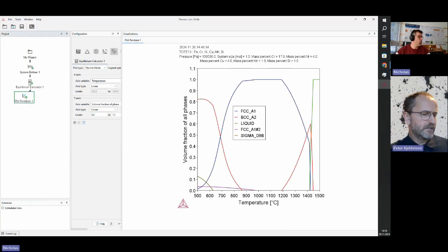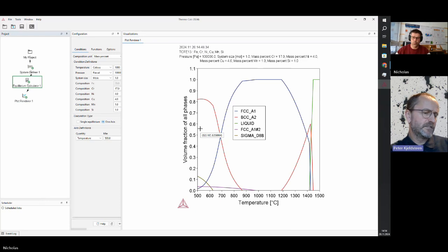Yeah. And we have, I think it's called a ferritic steel. I think you can make it magnetic, but typically it is used as a ferritic. So okay, the hardness of it comes from the precipitation. Without precipitation, it is not very high. When you get the precipitation, it can reach, I think, something like 40 Rockwell C, but not a lot. 40 Rockwell, and yield strength? Would you know? Mm, no, I might, but okay.